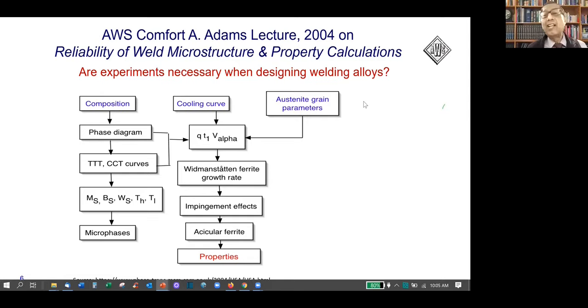This is again a slide I copied from his presentation, talking about steel composition, heating and cooling curves during welding, and austenite grain size. And from the composition, he uses thermodynamics to calculate phase diagrams, time temperature transformation diagrams, continuous cooling curves, martensite start temperature, all kinds of parameters that are needed to calculate, based on phenomenological understanding, the transformation of austenite to ferrite phases like Widmanstatten, acicular ferrite and grain boundary ferrite here.